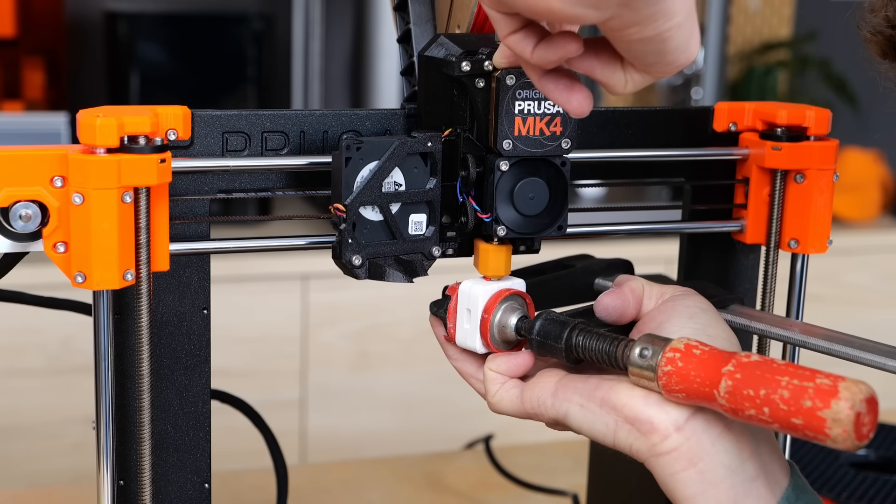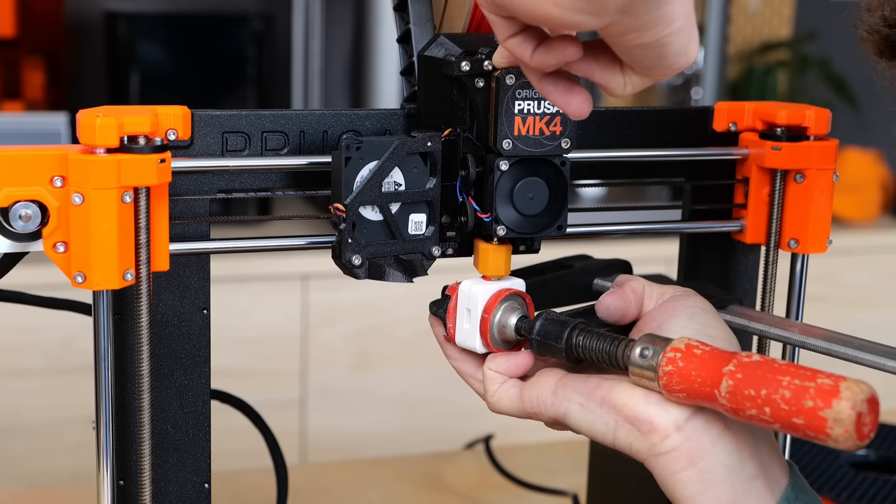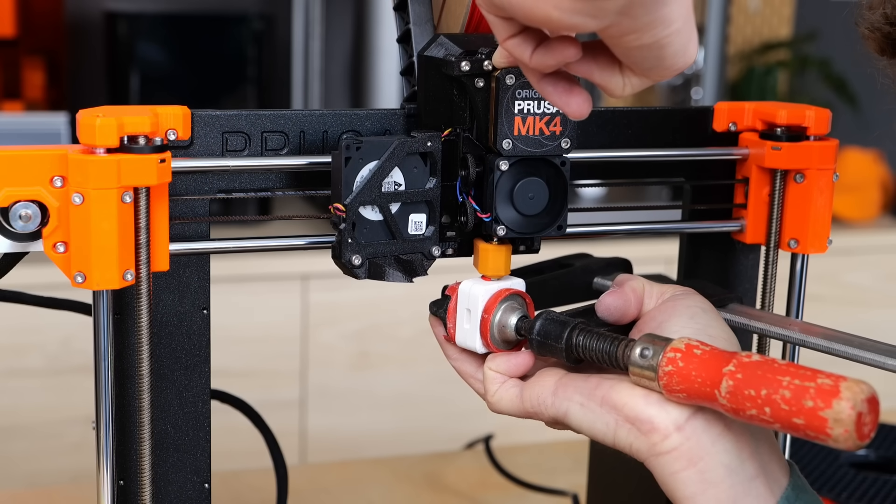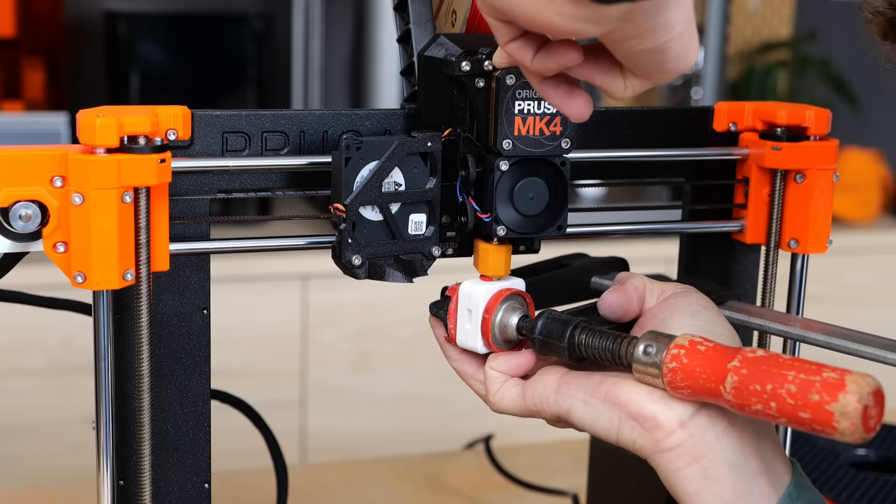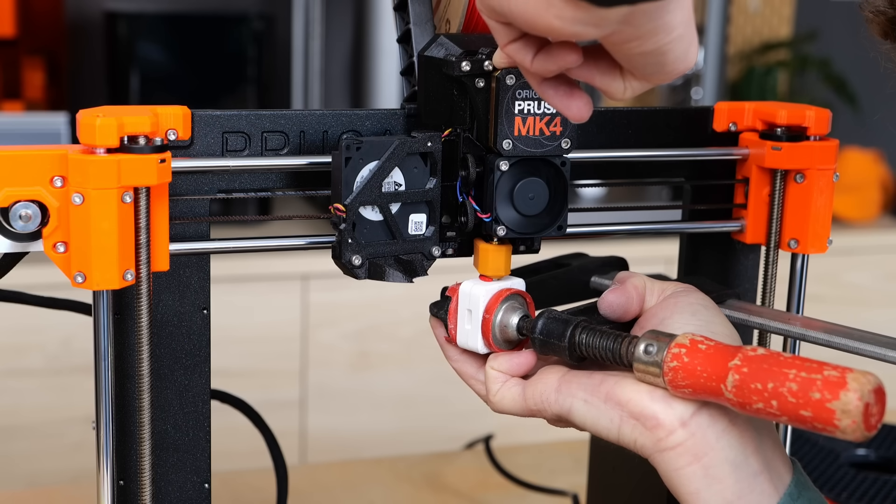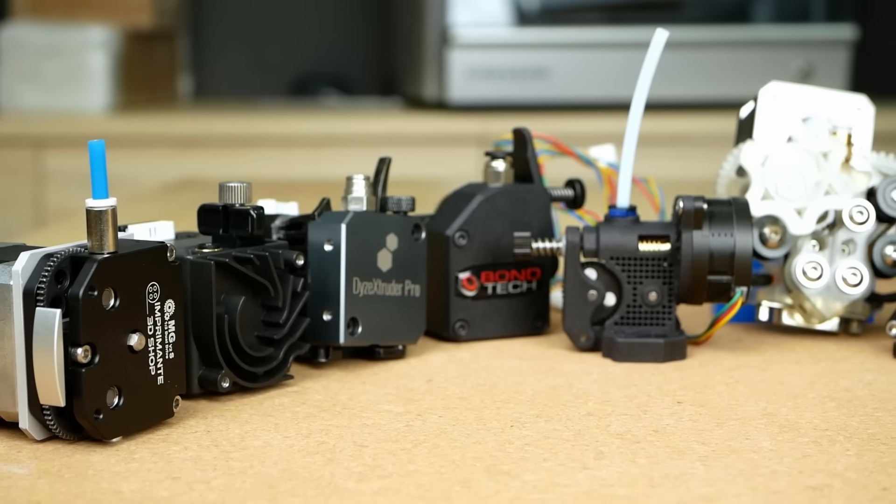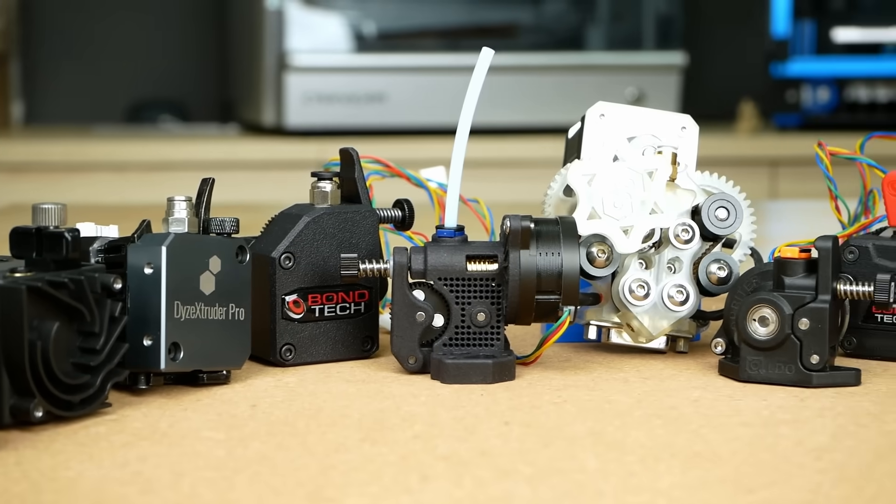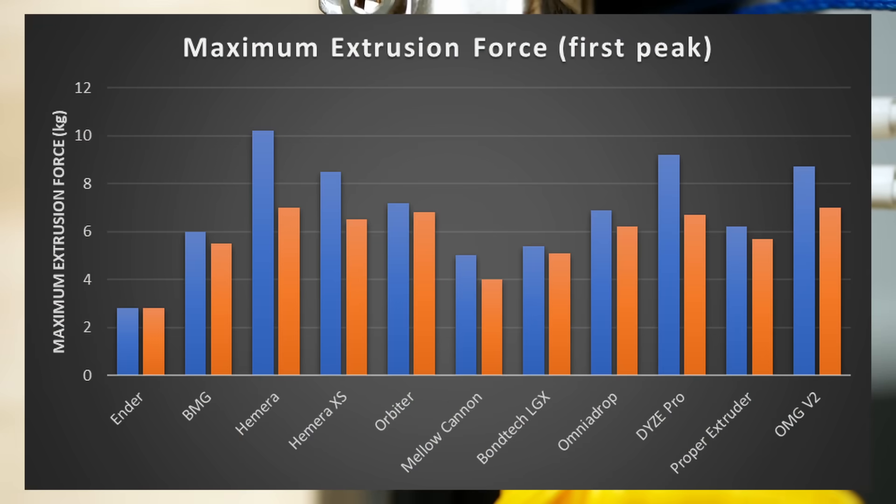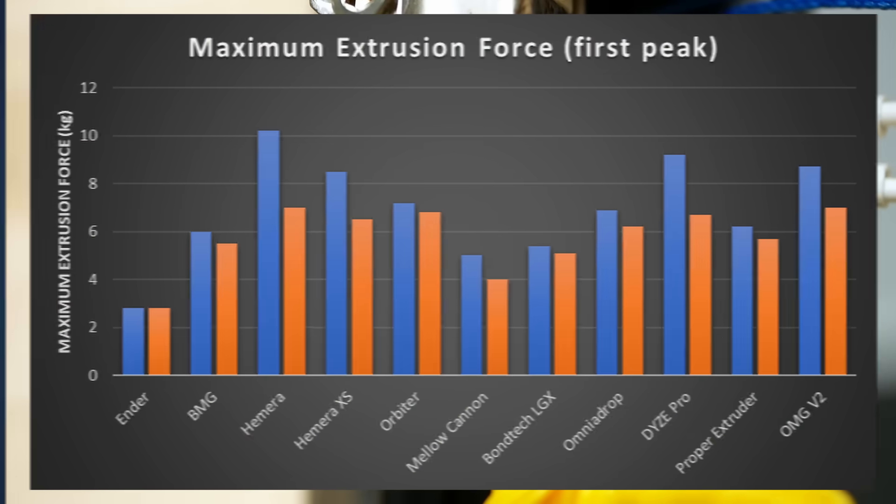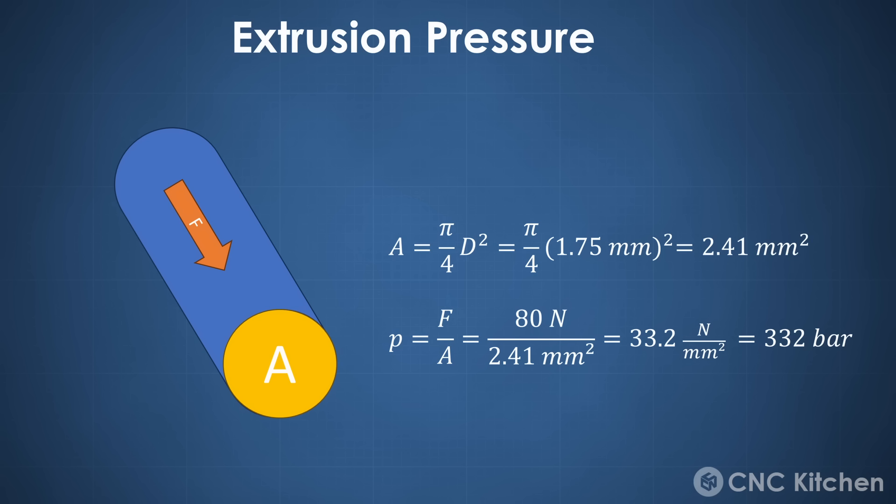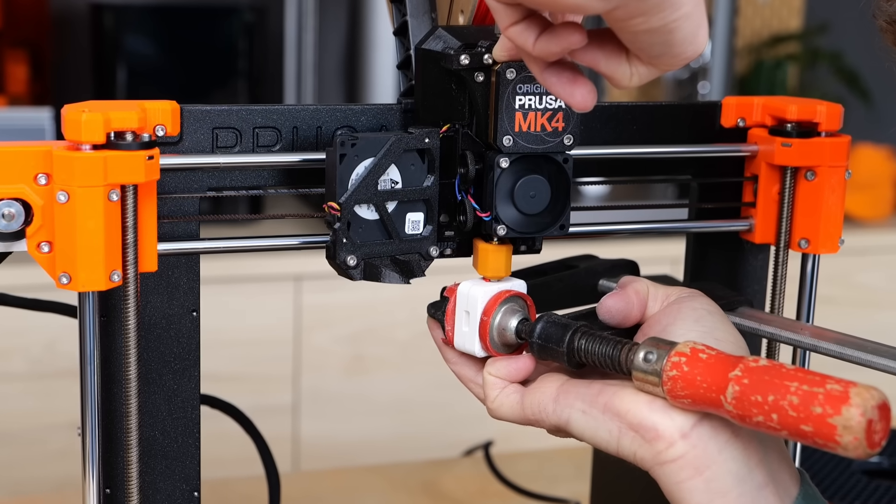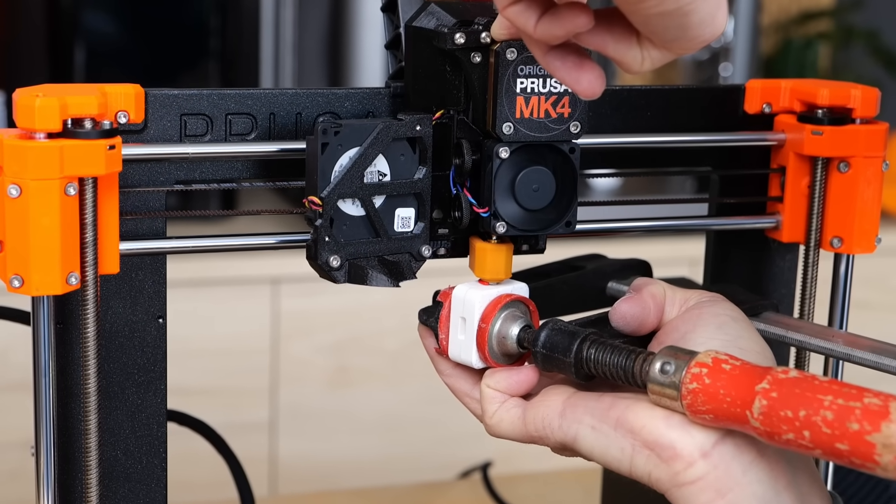In order to fill the mold completely we would need to increase the injection pressure, which is basically how hard we can push the filament into the mold and out of the nozzle. A while back I tested different extruders in order to find out the strongest one exactly for this process right here. Most of them were able to push with a force between 6 and 10 kilograms. Using the cross-section of the filament we can estimate the injection pressure. At an average maximum force of 8 kilograms, the 1.75mm filament is able to create pressures of over 300 bars or almost 4800 psi. This is actually significantly more than I expected.